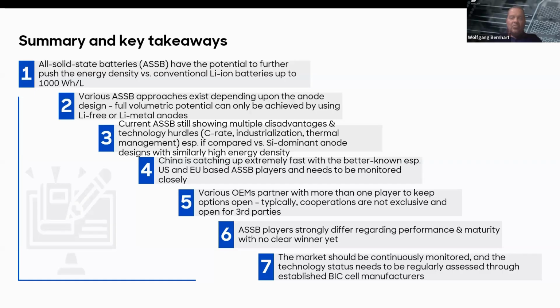where you really have a requirement for very high energy density, which is also true for some of the silicon players that focus, for example, on applications in aerospace or vertical takeoff and landing, where obviously every gram or every kilogram, every pound of weight matters double. So in those applications, price is typically not as big an issue. Companies are willing to pay double, 3, 4 times the price than what we see in automotive. But that would not fill up a gigafactory. That's the issue.